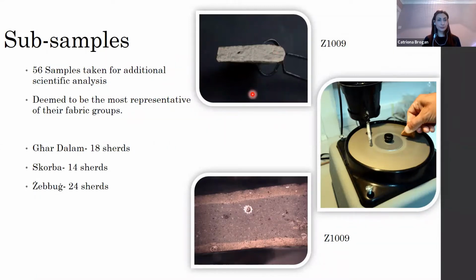So in order to get a better idea of the different fabrics that each period had, we decided that we needed to grind a flat surface on each of the sherds. And then this allowed us a much better view of the fabric itself. So this is the same sherd before and after grinding, and with this one you can start to see the dark core, the lighter margins, and we can see the clays and the material within the sherd itself.